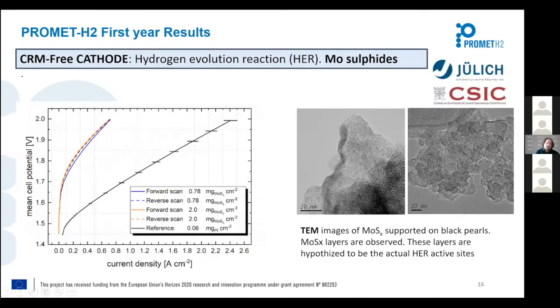Regarding the critical raw material free for the cathode side, for the hydrogen evolution reaction, we will use a molybdenum sulfide. This work was done by, the catalyst was developed by the CSIC, and also the membrane or the MEA was prepared by Jülich. In this graph here on the left side, you can see the comparison between the reference that is loaded with platinum and the performance with these molybdenum sulfides at two different loads.